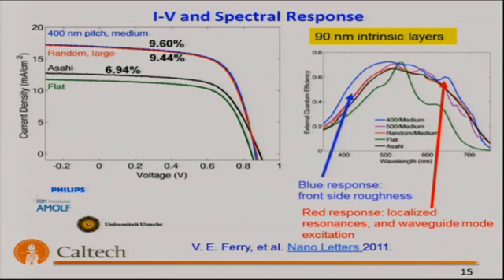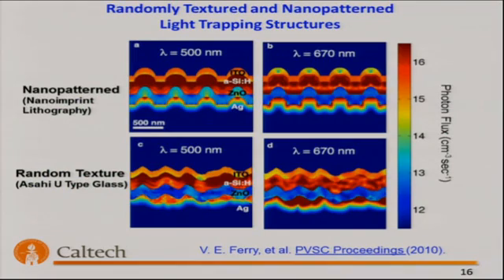Asahi glass, that are coated then with silver to form a back reflector, something that looks like this. And this is a full-wave simulation of such a structure here, a randomly textured glass surface coated with silver, zinc oxide, PIN amorphous silicon. And what you find is that this random texture is non-optimal for the balance between parasitic absorption in the metal and scattering into the semiconductor.